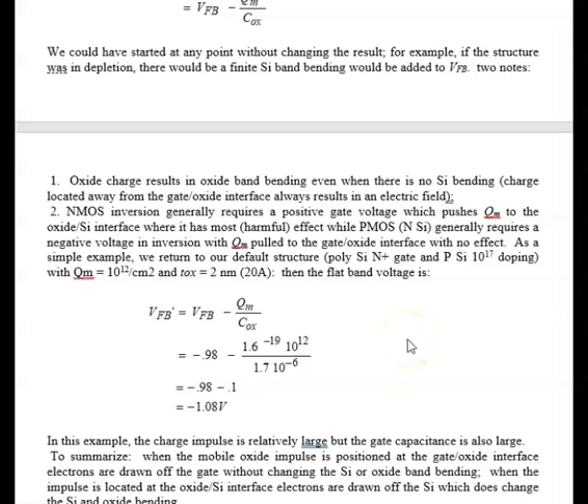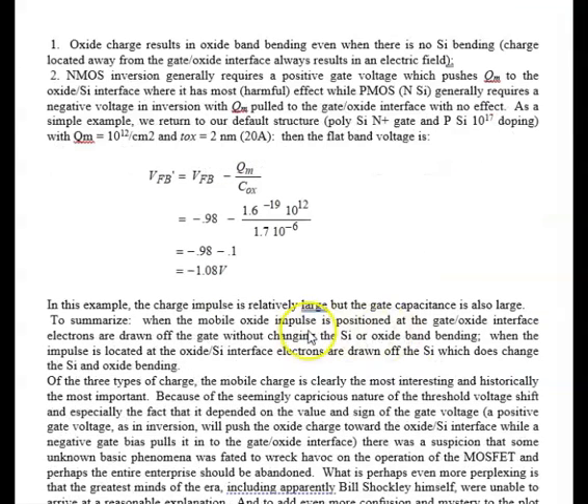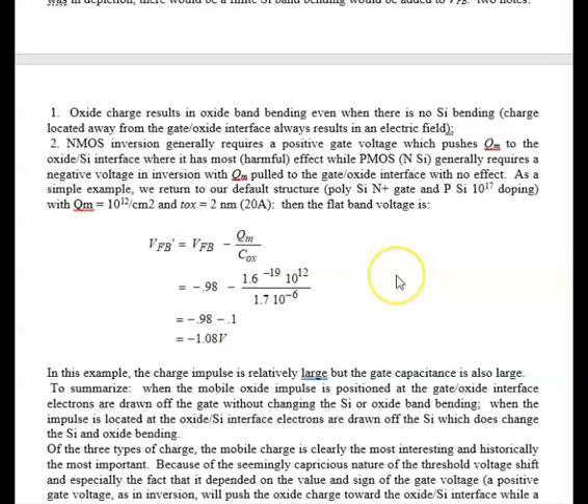So just to summarize again, when the mobile charge is positioned at the gate oxide silicon, the left side, it has no effect because electrons are drawn off the gate, an inexhaustible supply of electrons, and we don't change the silicon or the oxide band bending at all. However, when the impulse is located at the oxide silicon interface, electrons are drawn off the silicon, and that does change the silicon and or oxide band bending.